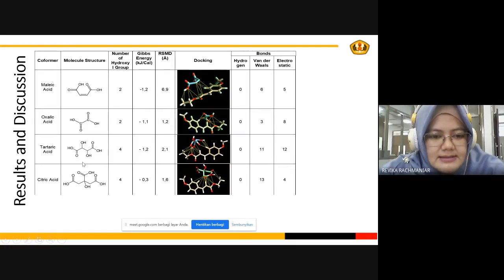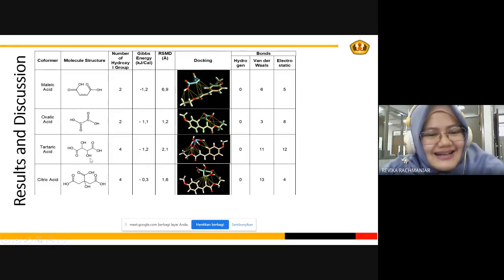From my analysis, tartaric acid and citric acid have 4 groups, but the distance between the hydroxyl groups is quite close. So probably they have a chance to interact with each other through hydrogen bonding, intramolecular, by themselves. Maybe that's my analysis.